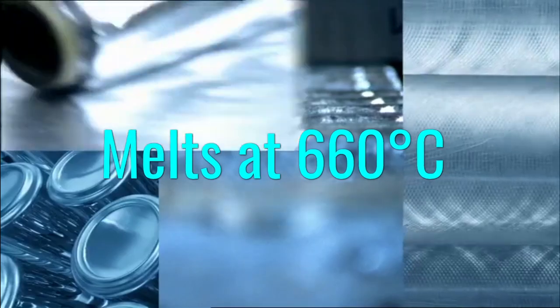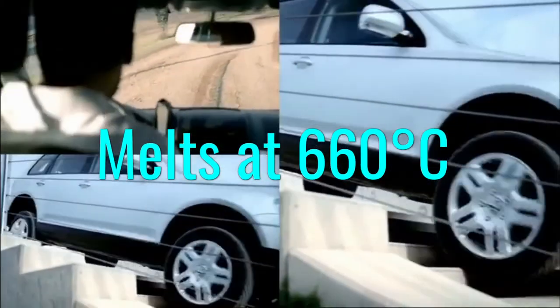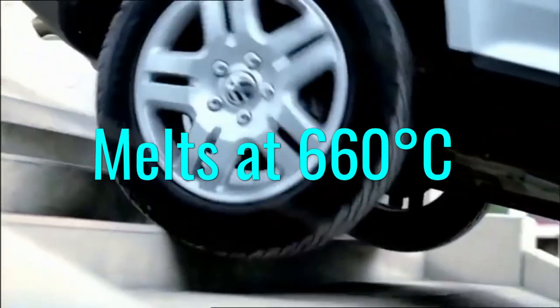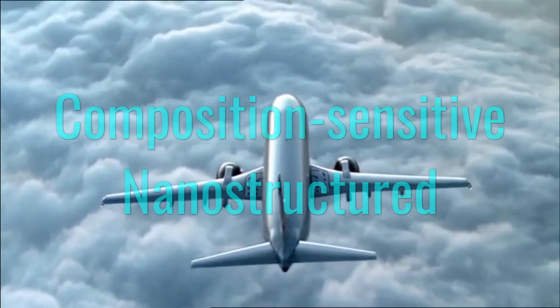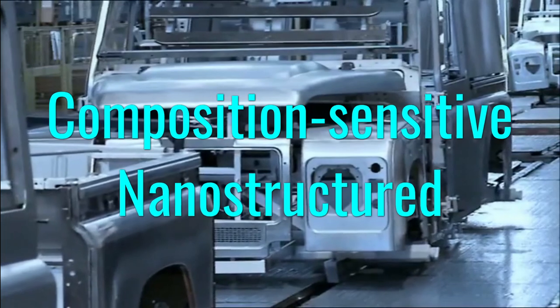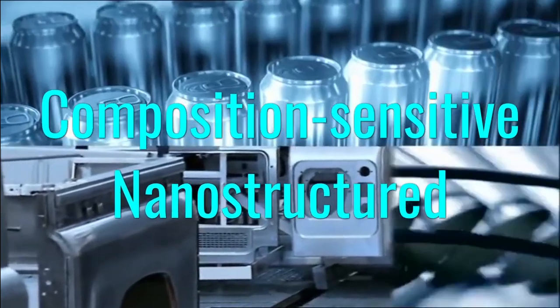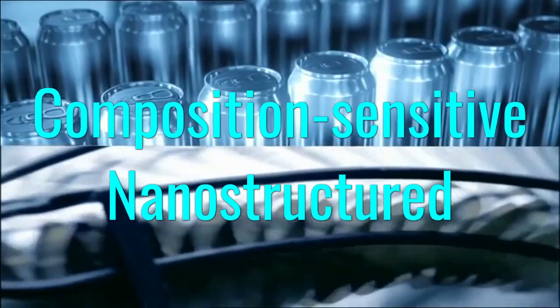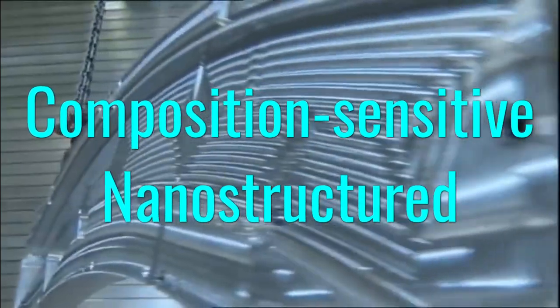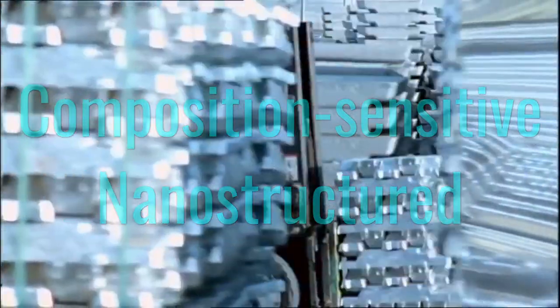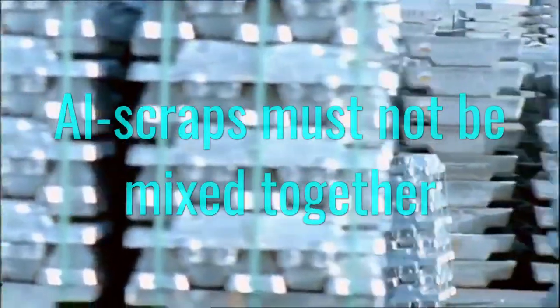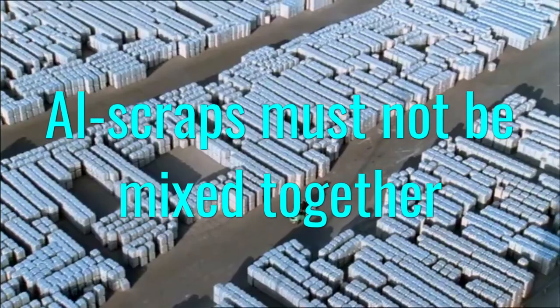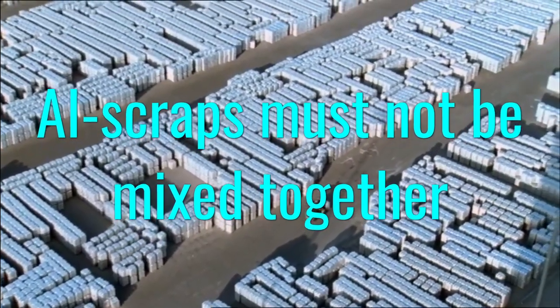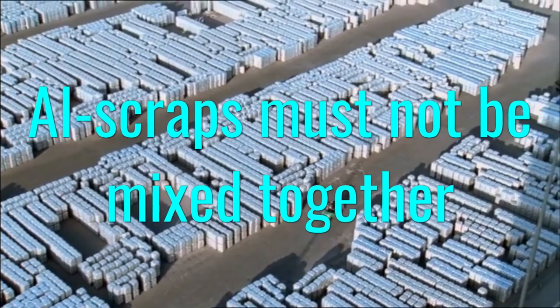This means that melting aluminium scraps into new material comes at very low energy costs, only 5% of what is used for its primary synthesis. However, aluminium alloys are also very composition sensitive and retrieve their good mechanical properties from a complex set of nano-precipitates. Therefore, aluminium alloys should not be mixed, but require very good scrap separation prior to recycling.